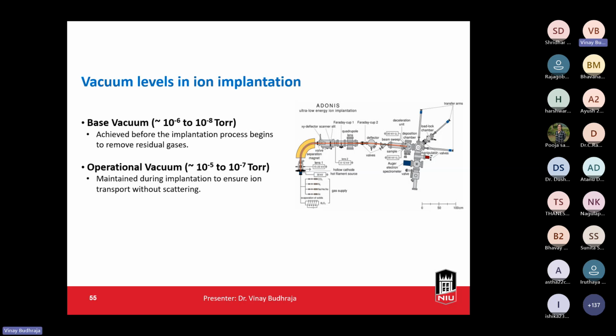The vacuum levels used in ion implantation are 10 power minus 6 to 10 power minus 8 torr for the base vacuum, and for the operational vacuum, it's 10 power minus 5 to 10 power minus 7 torr. The base vacuum removes the residual gases from the chamber first, and the operational vacuum is maintained during implantation to ensure ion transport without scattering. So ions have to be transported from the hollow cathode hot filament source to the load lock chamber.